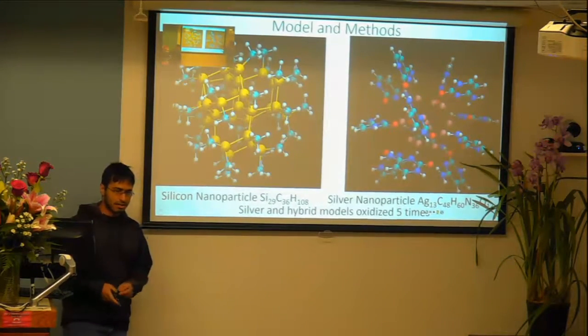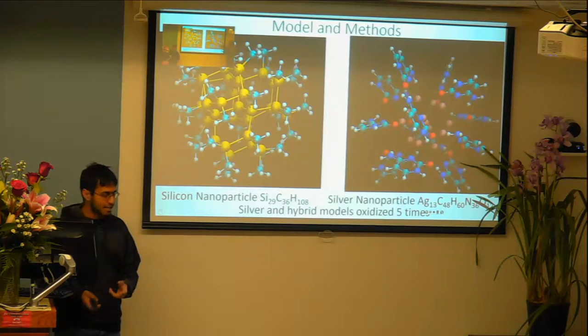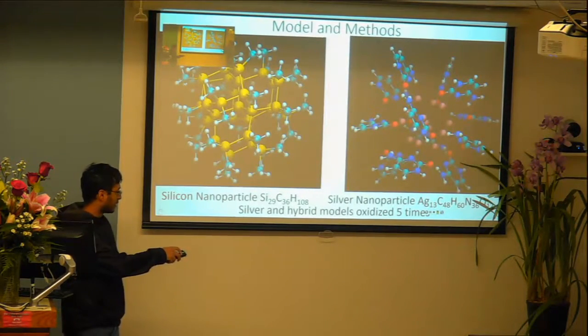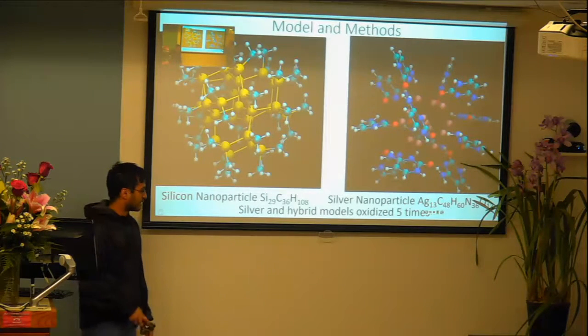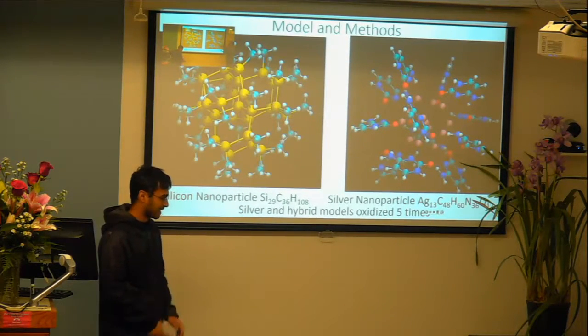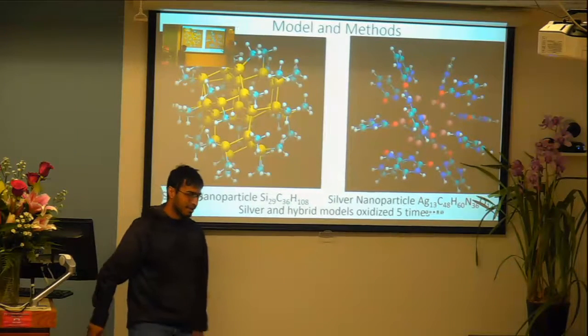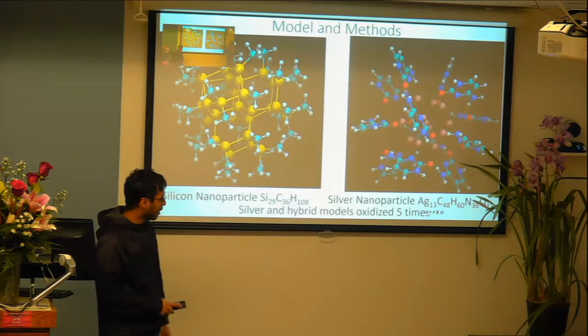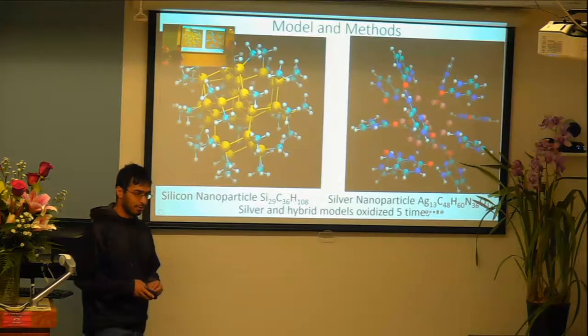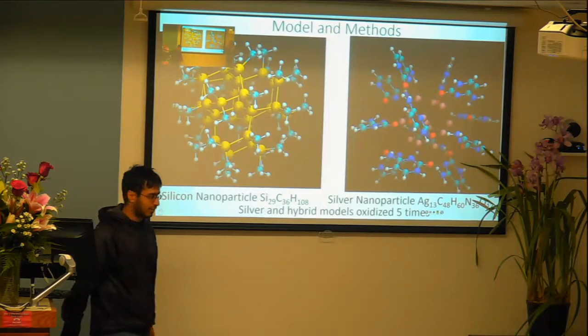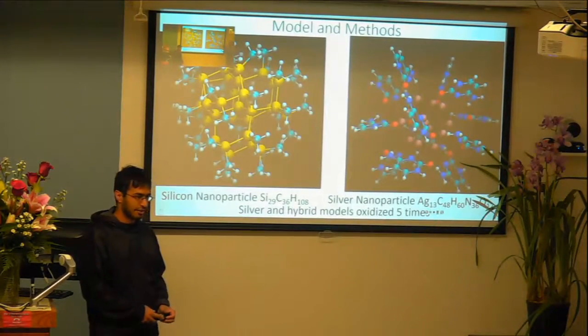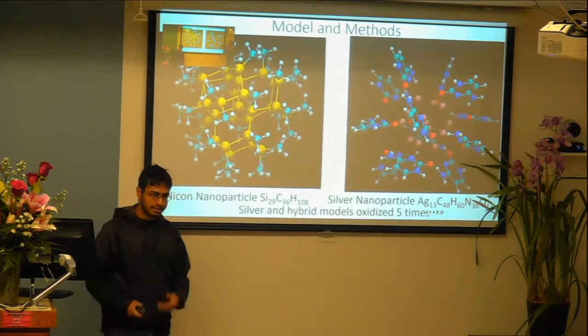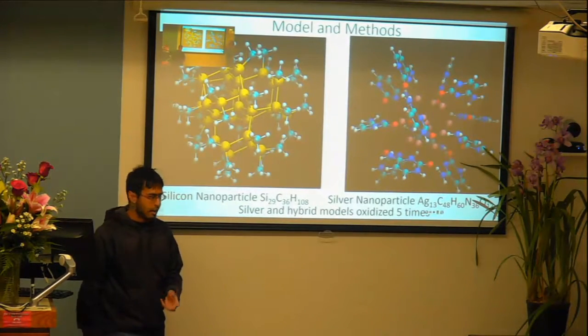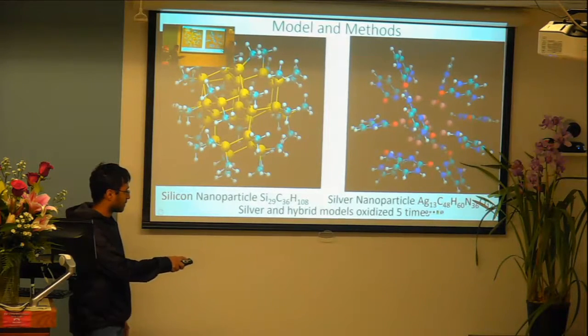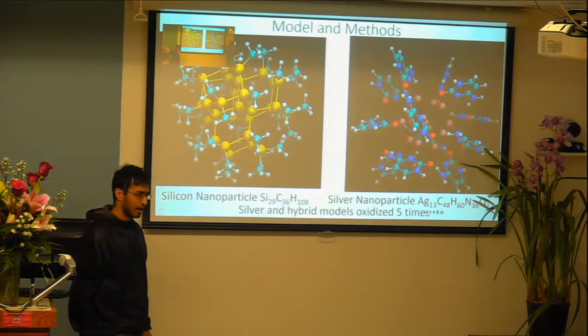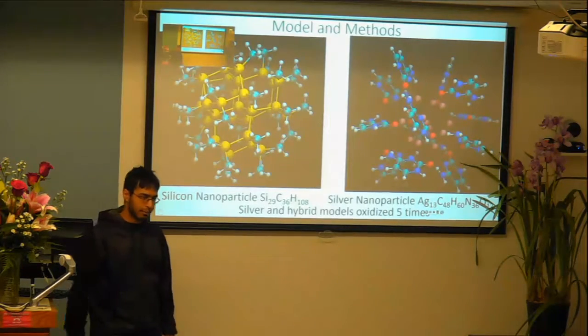And for the purpose of our simulations, which were run in VASP, the silver and hybrid models were oxidized 5 times. So this means that from the neutral model, we actually removed 5 electrons from the model when we were running simulations on them. And this was to explore different oxidized states for our model.